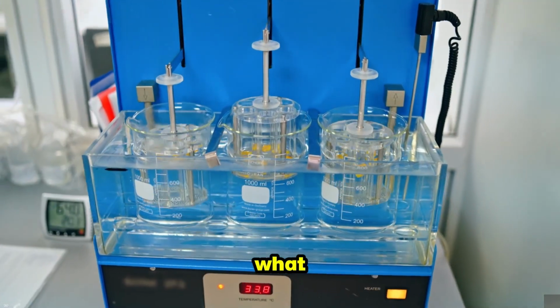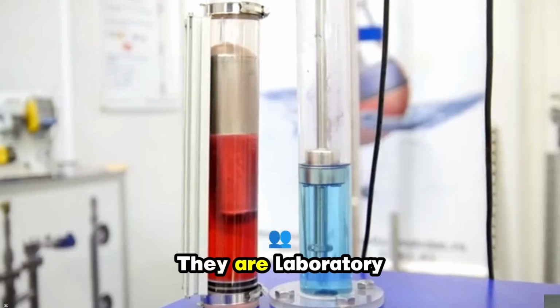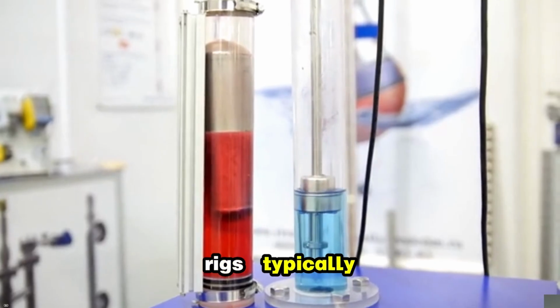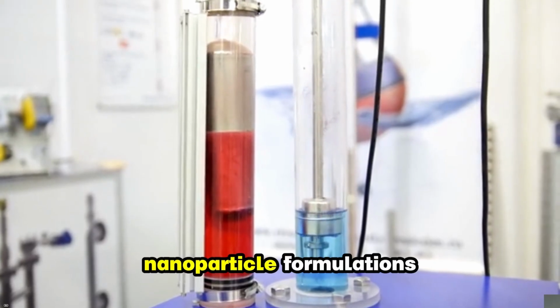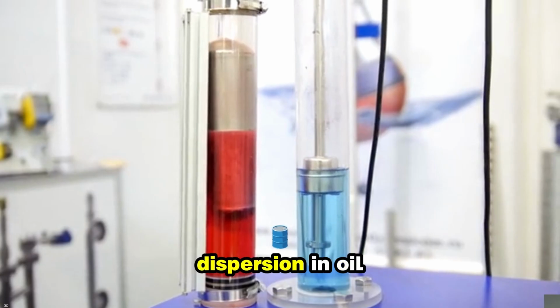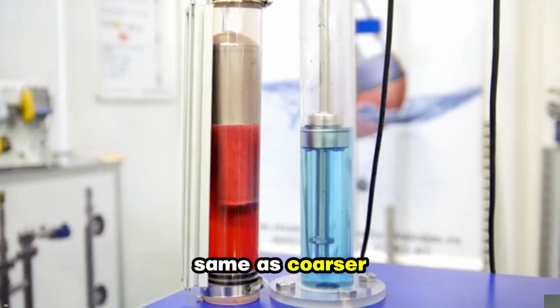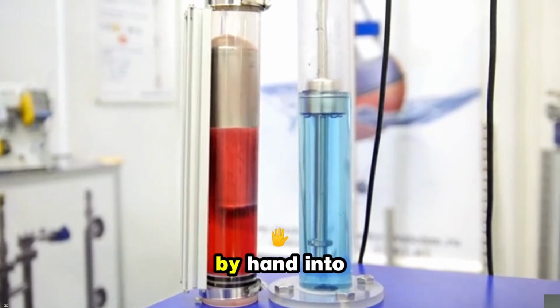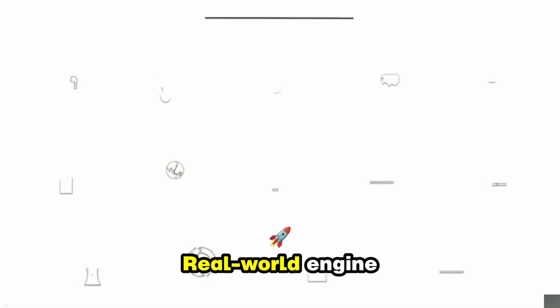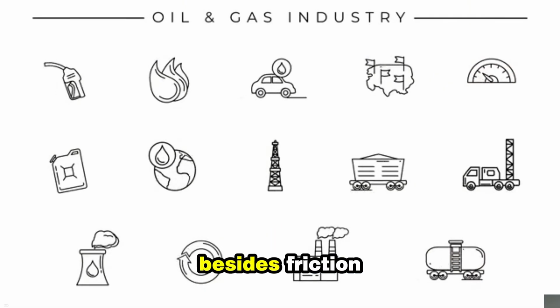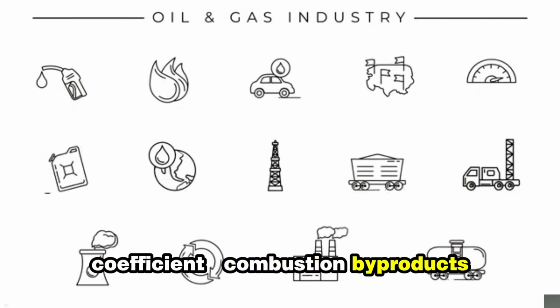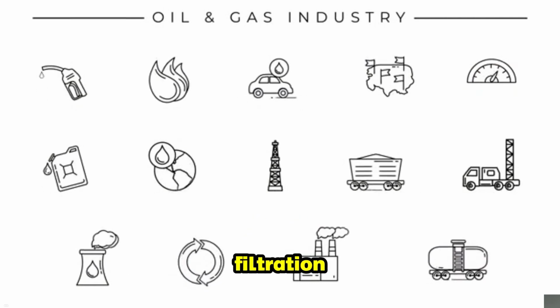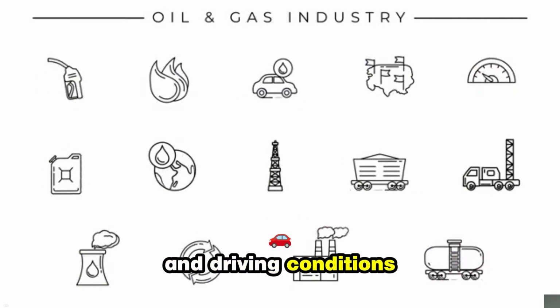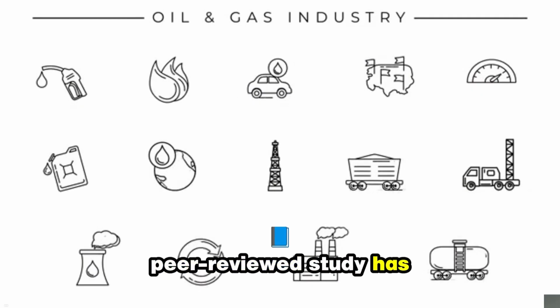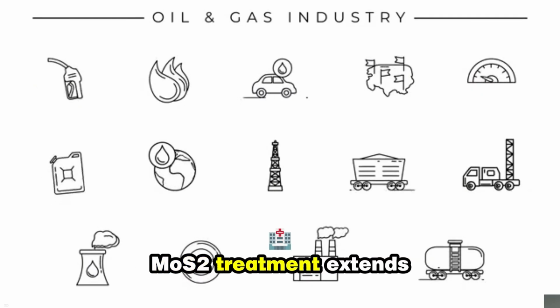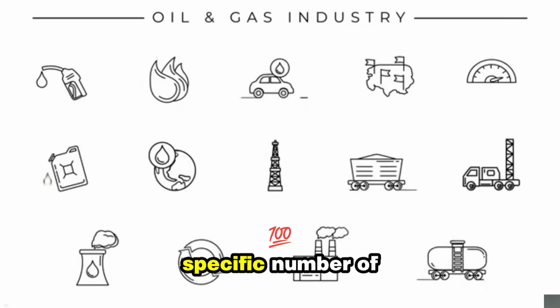It's worth being precise about what these studies do and don't show. They are laboratory results from standardized rigs, typically 4-ball tribometers, using engineered nanoparticle formulations designed for good dispersion in oil, not necessarily the same as coarser, technical-grade MoS2 powder, mixed by hand into a road vehicle's crankcase. Real-world engine longevity depends on many variables besides friction coefficient: combustion byproducts, oil chemistry, particle settling and filtration, seal compatibility, and driving conditions. No peer-reviewed study has directly measured whether a home-mixed MoS2 treatment extends real-world engine life by any specific number of miles.